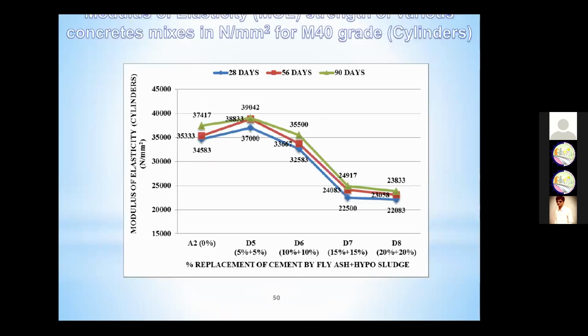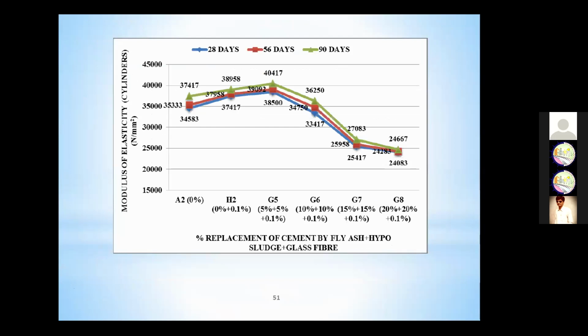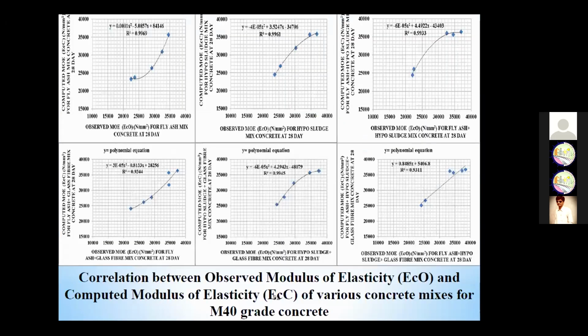Then the predictions regarding this modulus of elasticity for M40 grade of concrete. Same way with the glass fiber addition in the modulus of elasticity in the M40 grade of concrete, and their observed MOE and computed MOE are near to 1.